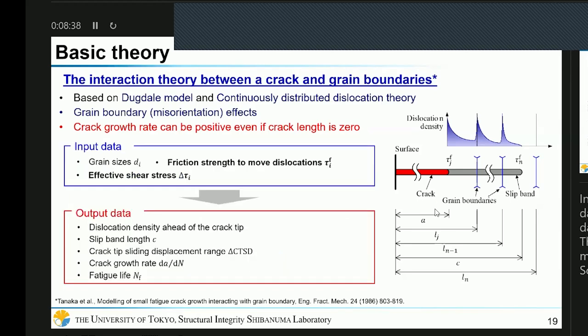So anyway, using this model, using the information about grain sizes, friction strength to dislocations, and the effective shear stress as the input data, we can obtain dislocation density ahead of the crack tip, slip length, crack tip sliding displacement range, crack growth rate, and fatigue life as output data. So to perform this simulation, we need three kinds of input data. But grain sizes can be obtained from the microstructure model. So we have to evaluate the friction strength to move dislocations and the effective shear stress.